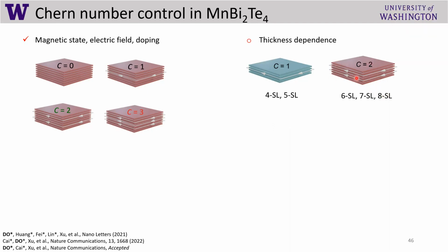So we see quantum Hall states only when we get to 6, 7, and 8 layers. The reason is not super clear to me. It might be related to the fact that when your sample becomes thinner, disorder becomes more important. So your mobility in thinner flakes could be lower, and that prevents us from seeing the Chern number 2 state, which, as I said, is a quantum combination of the quantum Hall state and the Chern insulator state. Possibly a thicker sample is more robust to disorder, so we can see that quantum Hall state.